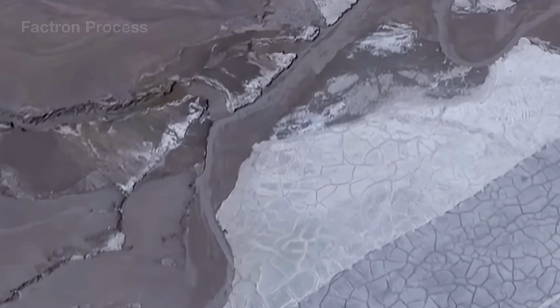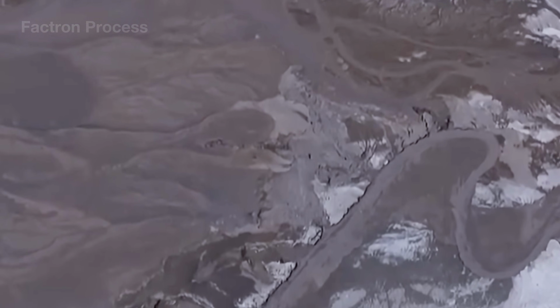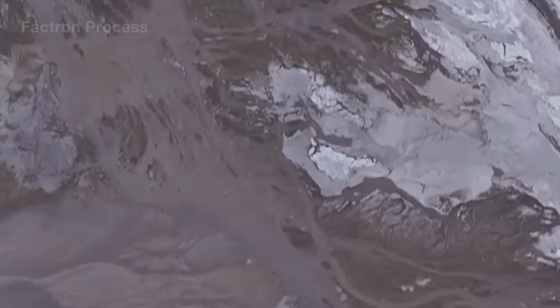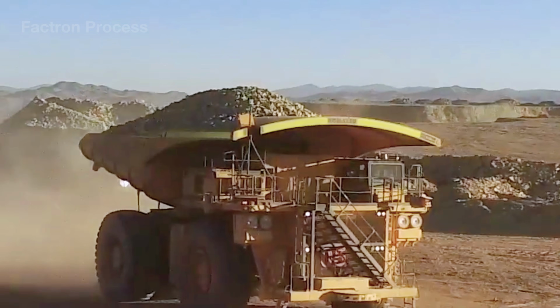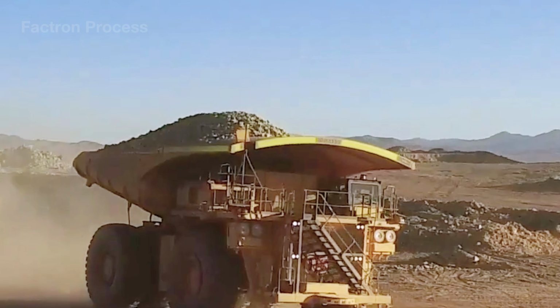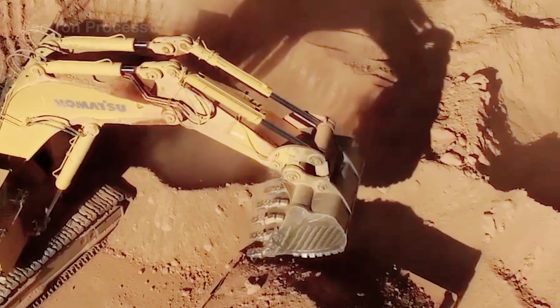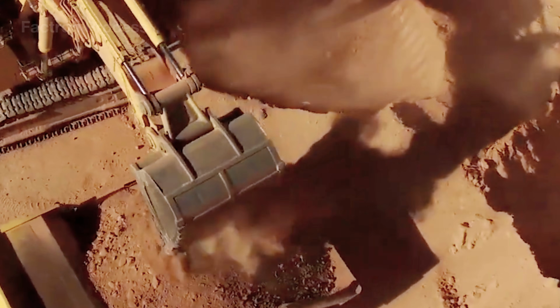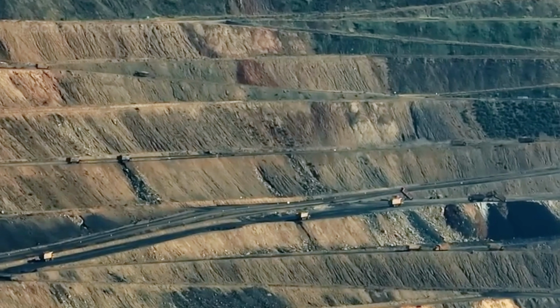The journey to create supermagnets begins at Bayan Obo in Inner Mongolia, China. A massive rare earth mine often estimated to hold more than half of the world's known reserves. Here, engineers conduct exploratory drilling, analyze core samples, and map ore bodies to identify carbonate rock zones rich in bastnäsite and monazite. High-pressure drilling rigs then create hundreds of holes more than 20 meters deep with drilling speeds that can reach approximately 5 feet per minute, before the holes are loaded with ANFO explosives.